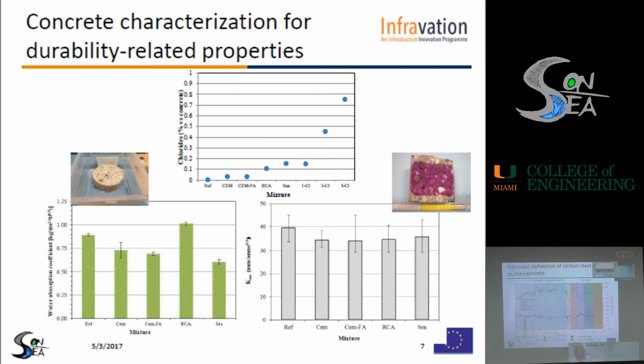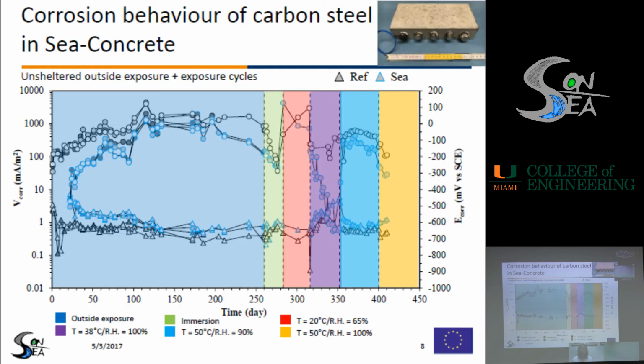In order to study the corrosion behavior of carbon steel in sea concrete, reinforced slabs were cast. These slabs were exposed to different environmental conditions. Before that, they were exposed to an unsheltered outside exposure in Milan, and then some exposure cycles were done varying the temperature and the relative humidity. These tests were carried out in order to simulate a structure where no further chloride penetration is expected.